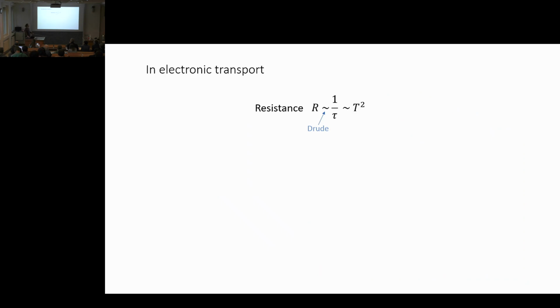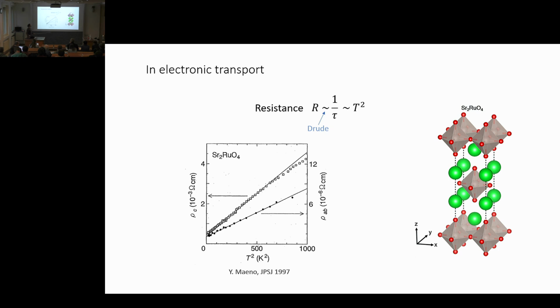Which means in transport, the resistance is directly proportional to the inverse of the lifetime, or the scattering time, so to T squared. Our stereotypical Fermi liquid of the day is going to be strontium ruthenate. In principle, it's a layered material, so we have different resistance in this layer than out of this layer. But what we can see if we measure the resistance is that the resistance really follows perfectly this T squared